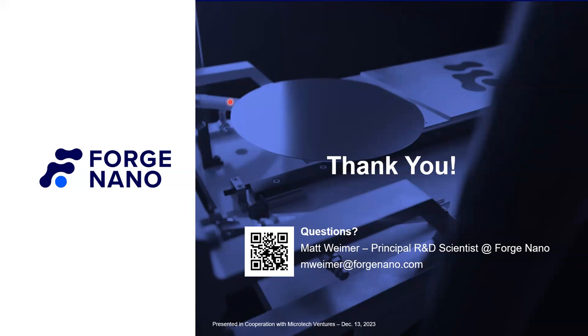The answer to that question is process dependent. What that means is it will depend on the precursors you choose. I'll give you some general rules of thumb of where ALD can exist. There are ALD processes that will go down to room temperature. I've even seen some people play around with sub-room temperature ALD, but let's not go there. Traditionally, ALD will, depending on the precursor, be 300, 350, maybe 400. When you get into ALD with halides, like aluminum trichloride or similar halides, you can even go up to 500 C. But for TMA water, I'm a firm believer that TMA will start to decompose right around 300, 315 degrees Celsius.